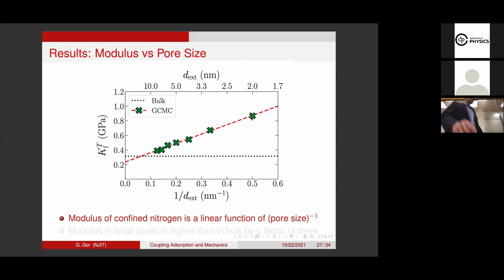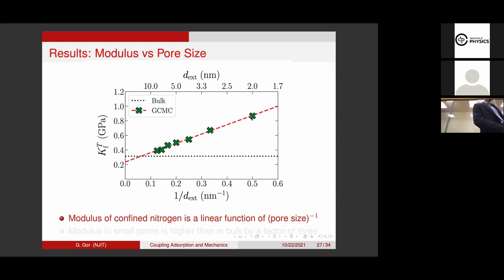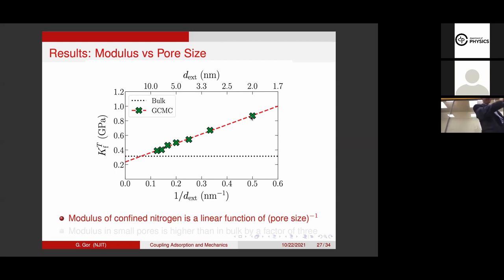In terms of absolute values — this is 0.3 GPa and this is almost 0.9 GPa — that's a huge effect. For supercritical methane in carbon pores, which is more of interest for petroleum applications, the effect is a factor of seven because supercritical methane is much more compressible, and it appears much more sensitive to confinement effects. The bigger the pore, the closer it is to bulk — but would it saturate somewhere? My former PhD student Max had some data for maybe 14 nanometers which pretty much matched the bulk value, but we didn't get any further.